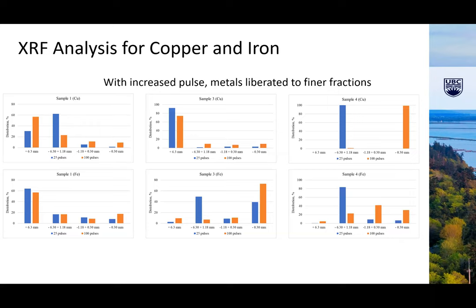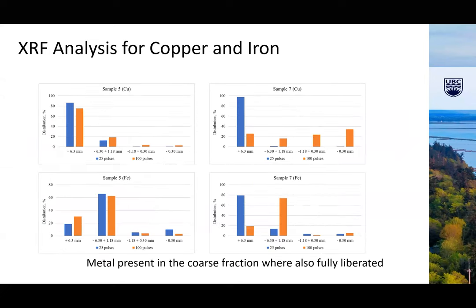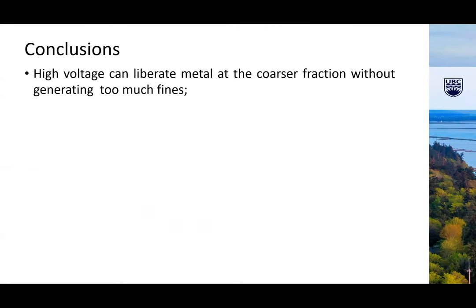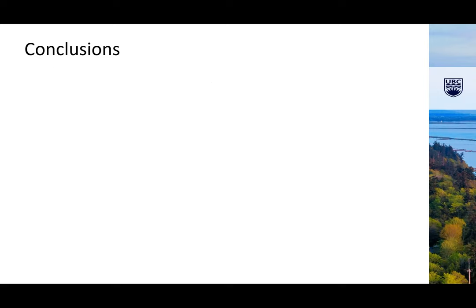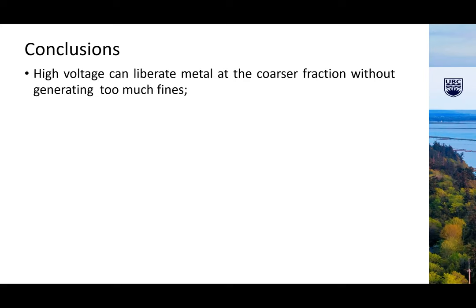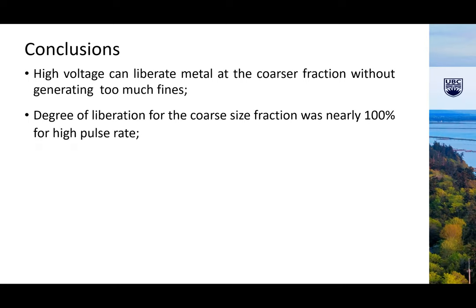With increased pulse, metals liberated also to the finer fraction, more for some types than others, but not considerably, not significantly. Metal present in the coarser fraction was also liberated. So a pretty satisfactory outcome out of this experiment. So high voltage can liberate metal at coarser sizes. So the conclusions were pretty straightforward.